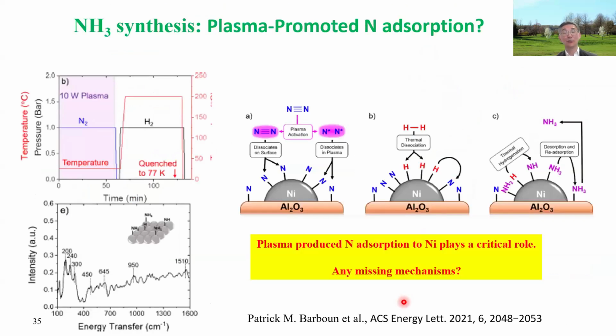Research always continues to evolve, and the same group, Bill Schneider's, used a nitrogen plasma to create vibrational excitation and nitrogen atoms. Then they turned off the plasma and flowed hydrogen at a high temperature. They started to see that the nitrogen atoms adsorb on the surface, run into hydrogen dissociated on the surface, and form ammonia. So they propose that ammonia production is through N-atom adsorption to the surface, which plays a critical role. If this is the truth, why do they need 60 minutes, 1 hour, to activate the surface adsorption? Plasma nitrogen adsorption on the surface only needs probably seconds or minutes. You don't need 60 minutes. So something must be wrong, or the answer is not complete.